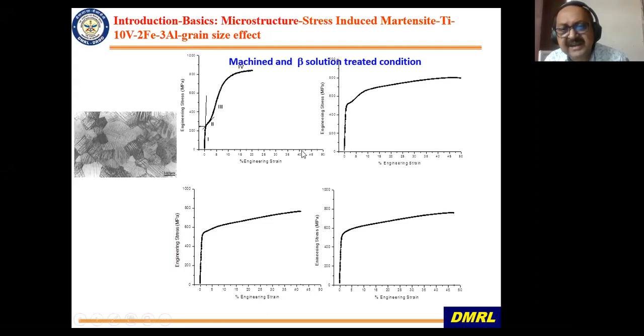And it is also grain size dependent. So you can get all sorts of tensile curves depending on the grain size that you have. Same material, different grain sizes, you will get different kinds of tensile curves. Although all are beta treated, you have treated at different temperatures. The bottom corner one is treated at 1200 degrees centigrade. Thereby the grains have grown very large, and there is very little transformation which will happen in this, and you will almost get a smooth kind of curve.